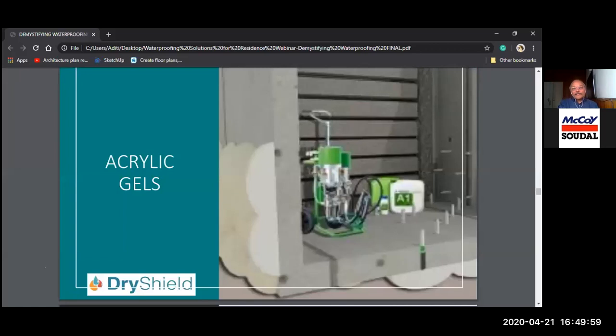Another good injection grouting for waterproofing is acrylic gel. In India, especially in the residential segment, at least I have not come across anyone using acrylic gels. These are expensive. This is for places where the water ingress is not stopping, and a drill has to be done across the wall, 9-inch or like 240 mm or 300 mm or 350 mm walls, and a layer has to be formed outside. So the acrylic gel is pushed outside the concrete wall, and it forms a gel layer outside the wall and stops water ingress. Among all the injection groutings, this is the best, but it is expensive and done mainly in large commercial buildings and large projects.